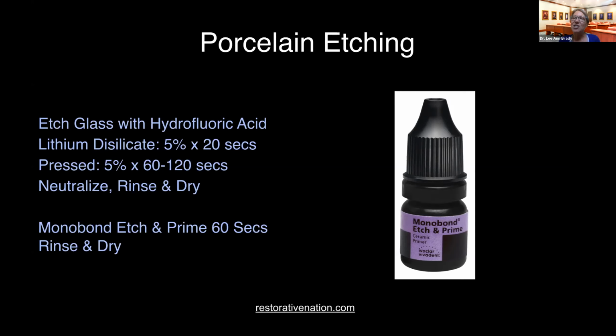You need to agitate it for the first 20 seconds of application time, and then you need to let it set a minimum of another 40 seconds for 60 seconds total as a minimum, but you can actually leave it on up to 6 hours and it will never be able to over-etch the glass. You can use Monobond Etch & Prime even if the laboratory has already etched the ceramic, and it will not over-etch the glass. It's physically incapable of over-etching the glass.